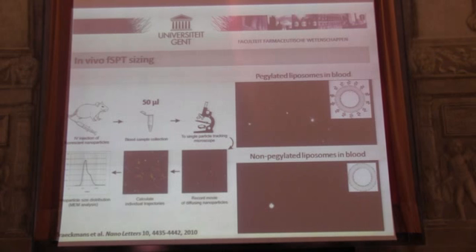We take at different time points small blood samples, so the rat is not euthanized, we just sting it a little bit. That's the only thing that the rat was suffering in this case. Very small samples. We bring it to the microscope and then we do these particle measurements. And I will show you two extremes, so that you appreciate visually what happens and what is the difference. So pegylated liposomes, you see they move very rapidly. They remain quite small. These non-pegylated ones, they aggregate, and you can see this already on site that this is a very big aggregate indeed.